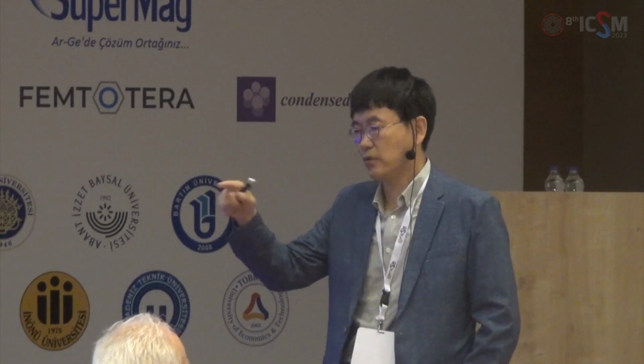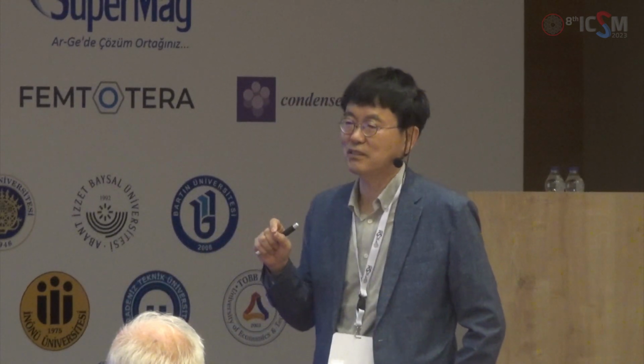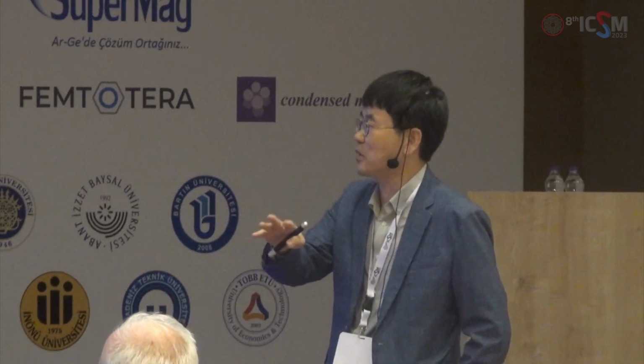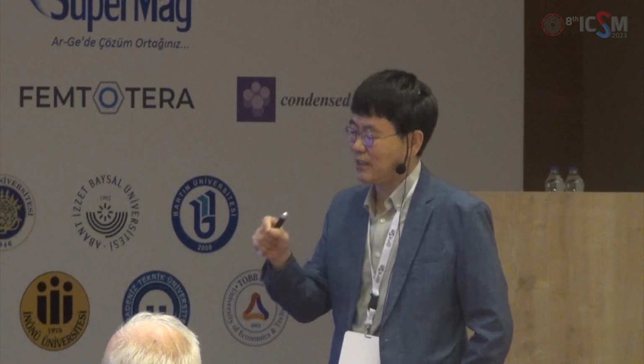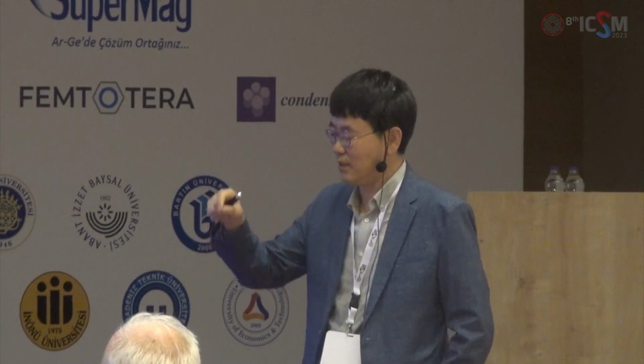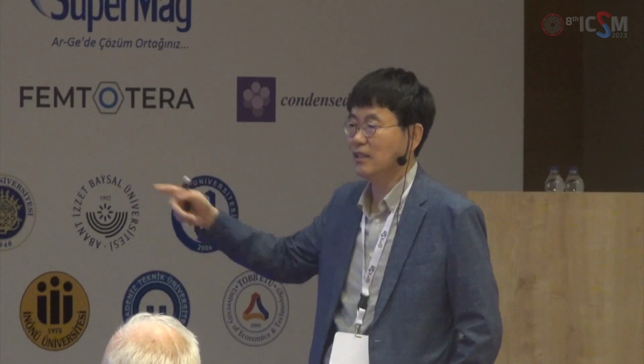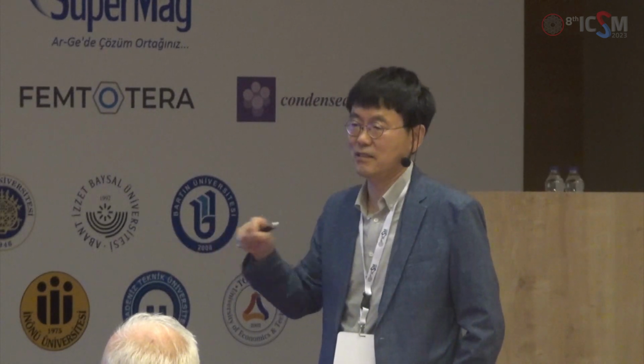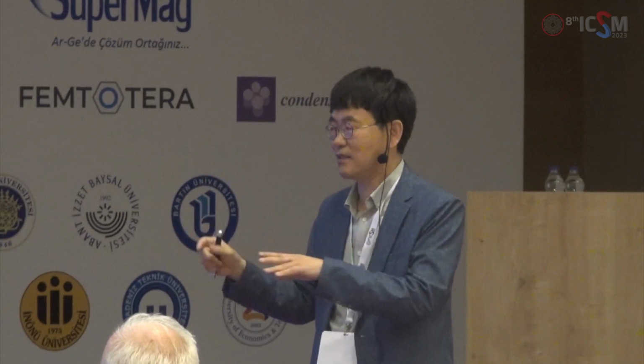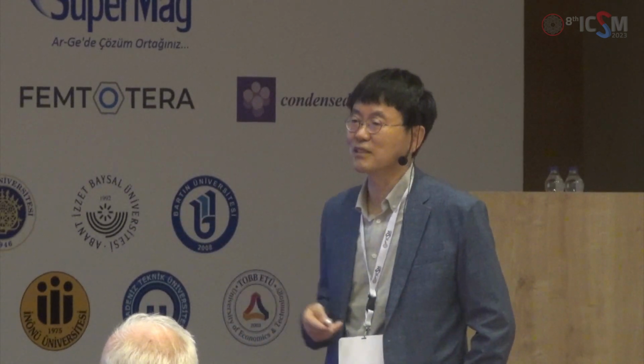So I assume whatever non-stoichiometry there was is sort of cured. But anyway, there can be a little bit of non-stoichiometry. There was one question from the referee. First of all, in strontium titanate, if there's a non-stoichiometry, you would expect some spectral weight and ferromagnetism, but as you see, our ARPES data shows absolutely no spectral weight at zero temperature. So we believe, I don't know up to what accuracy, but it's somewhat close to zero. Okay, thank you.